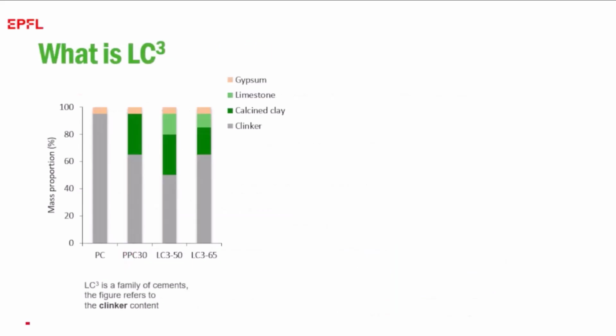Now, the essence of this is that rather than just having only a pozzolanic substitution, such as we might substitute 20 or 30% material with the pozzolan, by exploiting this synergy between the calcined clay and the limestone, we can replace another 15% of the energy-intensive clinker with limestone, which has virtually zero CO2 emissions. And you have a whole family of this. What we usually talk about is LC3-50, where the amount of clinker is just 50%, but you can have higher amounts of clinker. You can also have much lower amounts of clinker.